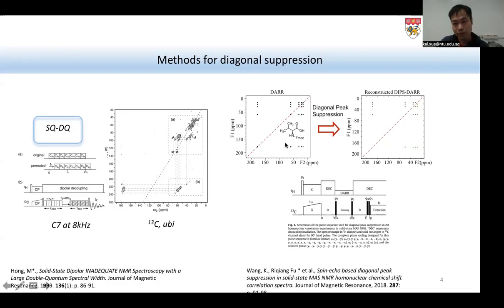And also for DARR spectra, Riqiang Fu's group proposed some phase cycling, and with reconstruction of the spectra afterwards, they managed to get diagonal-free DARR spectra. But this is specific to one scheme, and also, since we need to reconstruct the spectra, extra scans are needed, which don't contribute to the final sensitivity of detection.